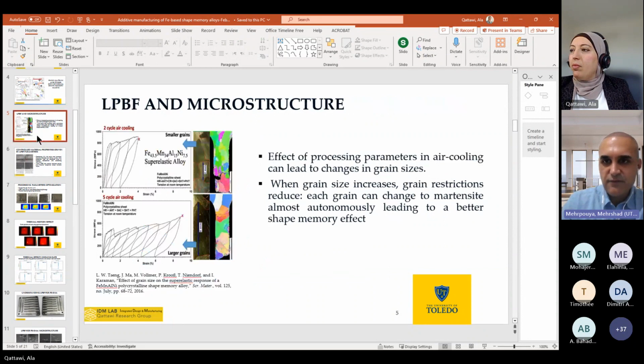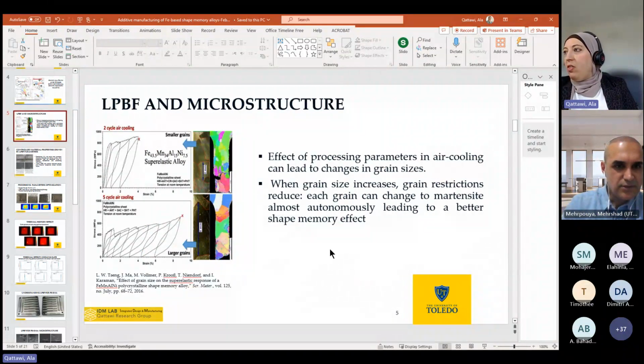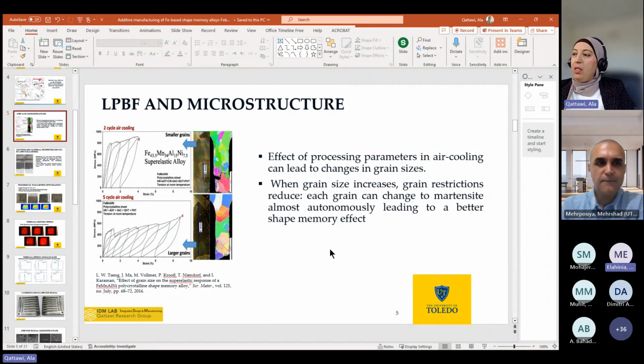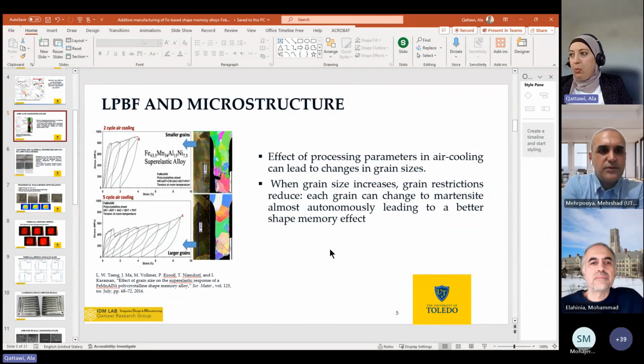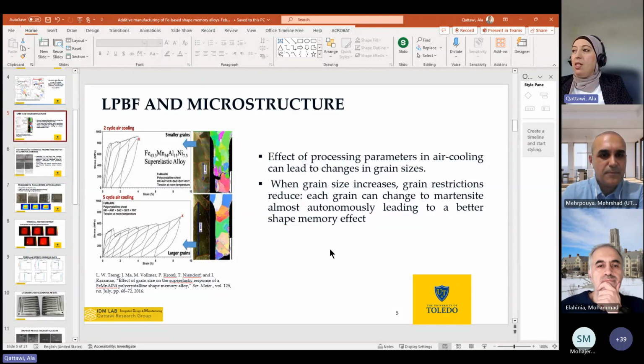Slide number 5. So slide number 5, this is where the cooling rate effect is shown, right? This is basically a traditionally manufactured polycrystalline shape memory alloy. And you can see that the different thermal signature of the process yields different grain structure. I cannot speak to why the grains in the traditional one show less ductility or higher, but this is a little bit different than the alloy system we specifically used, though it's within the same family.